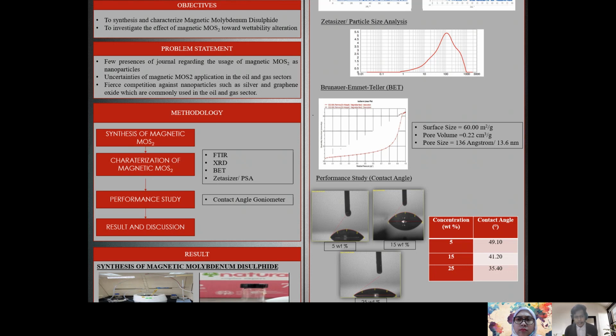After that, ammonia solution of 30% concentration is added to the mixture in order to ensure that the pH value will be 10, because the needed synthesis of iron oxide nanoparticles requires pH 10.